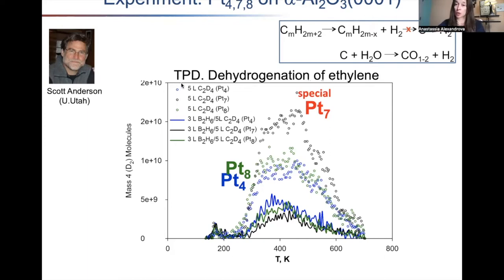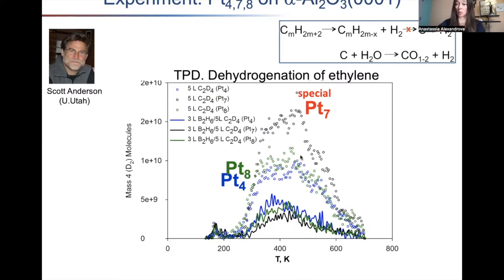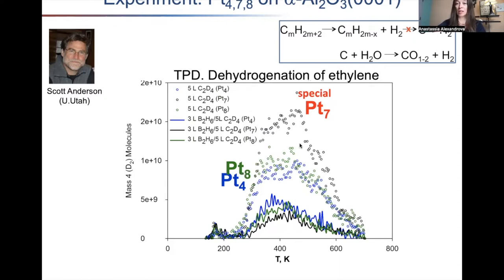We looked at temperature-programmed desorption (TPD) of deuterated ethylene. Scott prepares size-selected clusters, feeds deuterated ethylene, increases the temperature, and at a certain temperature he sees a maximum of D2 desorption from the deuterated ethylene. This temperature — for example for Pt7 — shows maximum activity, and the peak height tells us how active a given cluster size is.